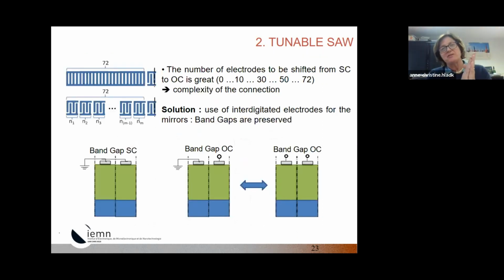But in the previous device, the problem is that the connections will be very complex. You imagine you have a great number of electrodes that have to be shifted from short circuit to open circuit. For instance, if you change from 0 to 10 electrodes, you need at least 10 switches to shift the components. So it's too much. The connections will be very, very complex. So we have to imagine how to simplify the connections, instead of using 10, 30, 50 switches, and have a very low number of switches.